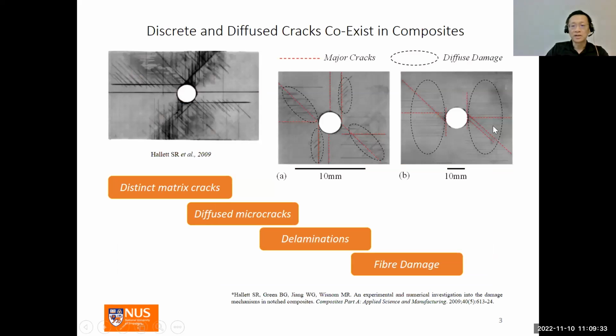Now, if you look at a typical notched composite specimen, such as an OHT specimen like so, you'll find there are combinations of distinct matrix cracks, diffused, very small but numerous microcracks, as well as delaminations and possibly fiber damage. Clearly, to capture the physics of these failure modes presents a huge computational and modeling challenge.